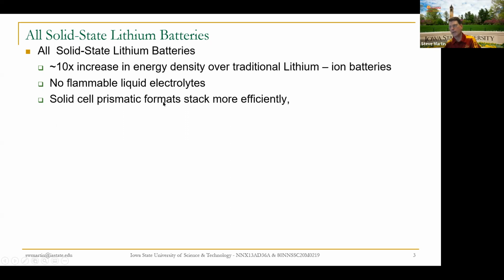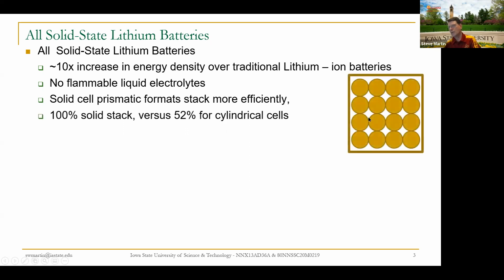And another big aspect in terms of reducing volume and reducing weight is the ability to form these solid cells. And so the Teslas, for example, that Elon Musk makes, they're all based on about 7,000 or so what are called 18650 cells, 18 millimeters in diameter, 65 millimeter tall cylinders. And when you stack cylinders, of course, you lose all this space. Well, Tesla and others utilize that space because they have to cool the batteries, they have to heat the batteries, they have to monitor temperatures and so forth, because the liquid electrolyte is very temperature sensitive.